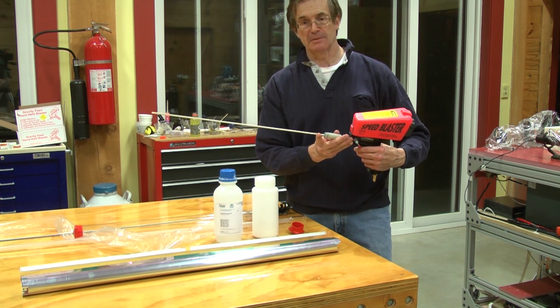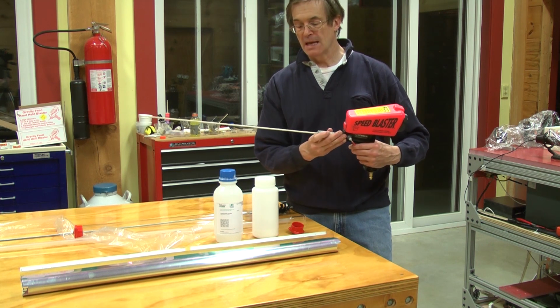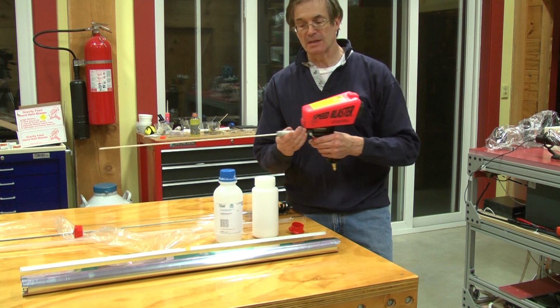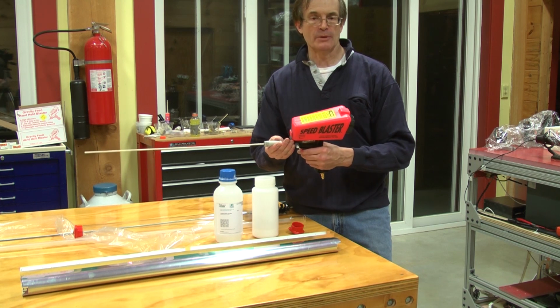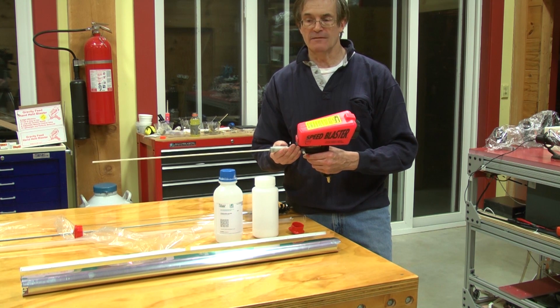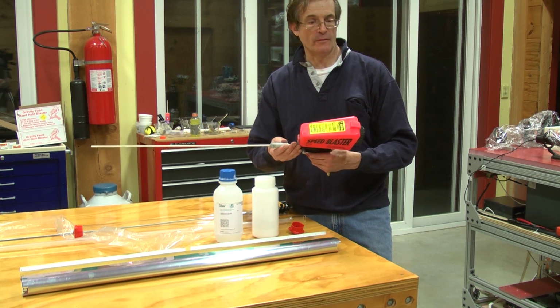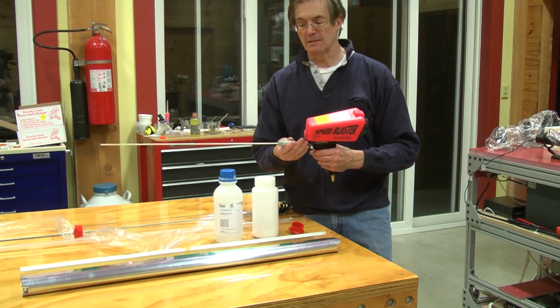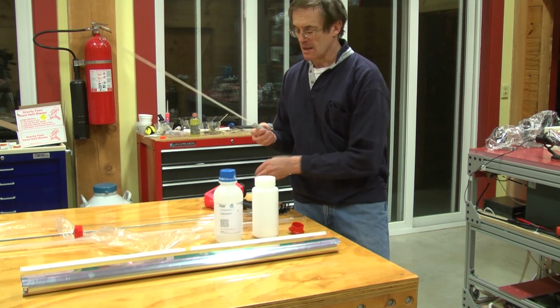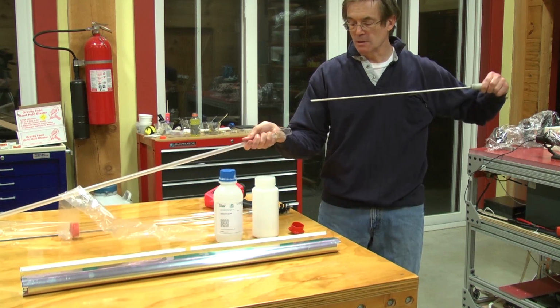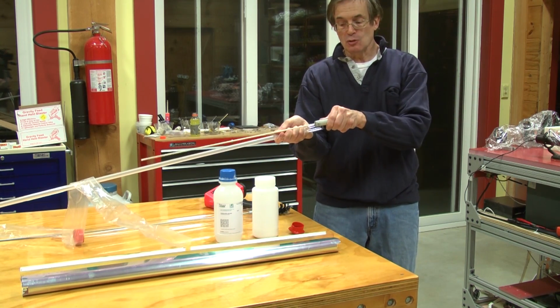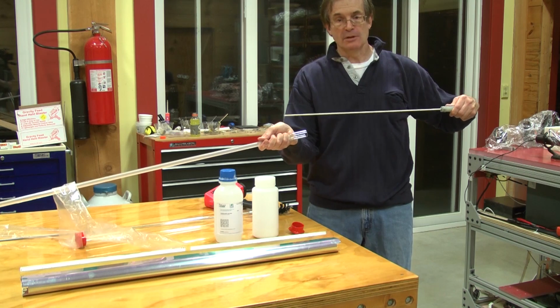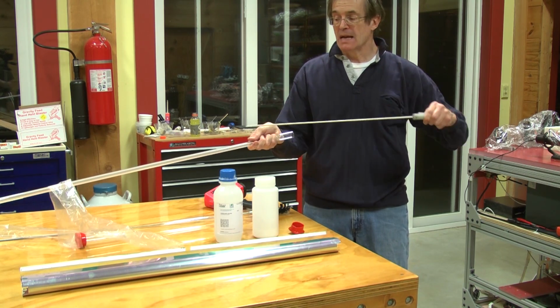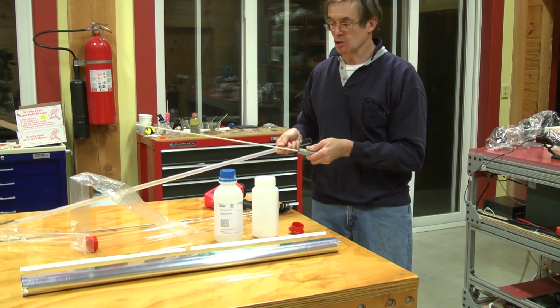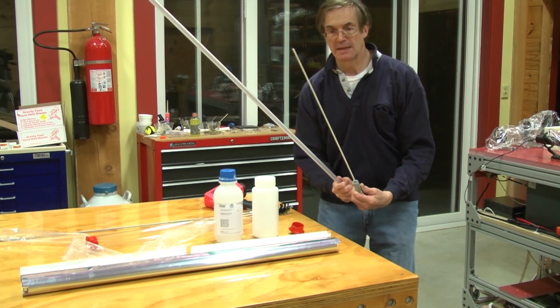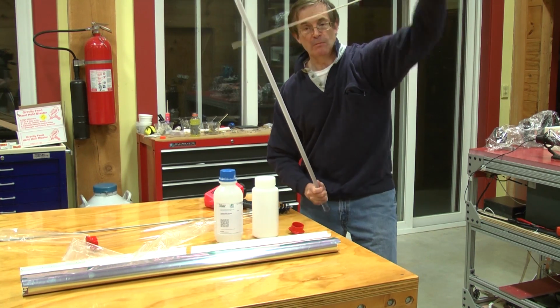And this alumina stands up to the abrasive material pretty well. You can then place this into even a tiny diameter tube. I mount them on a couple ring stands. I take a vacuum filter bag from a shop vac, tape it on the far end of the tube, and then I place this rod into the tube like this, insert it into the tube, and then begin blasting and drawing it out. And after a couple of random rotations, I then turn the whole thing around, because the tube is obviously longer than a convenient rod is, and so as a result, I blast it from both ends.